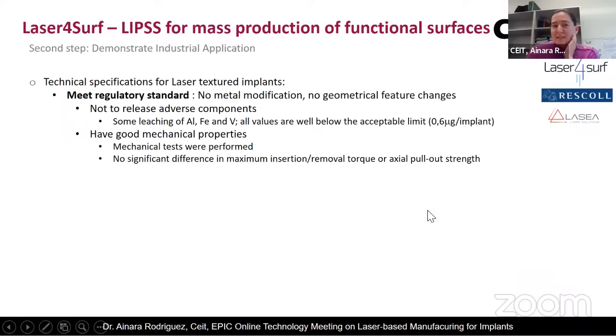So how about the regulatory standards? What we get when we make a laser texturing process on the surface of an implant? Well, we made some tests in order to see if we were modifying the chemical properties of the material. And we made a test of the particles that were released after the process with the laser. We saw some leaching of aluminum, also vanadium and iron from the component for the implant. But all the values were well below the acceptable limit that for this case is 0.6 micrograms per implant.